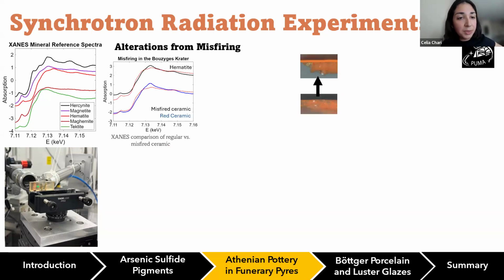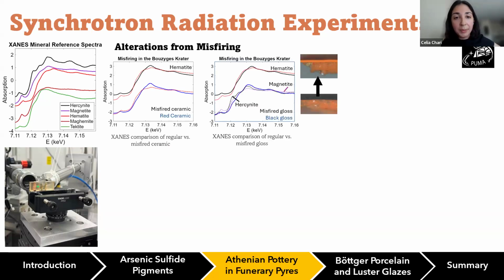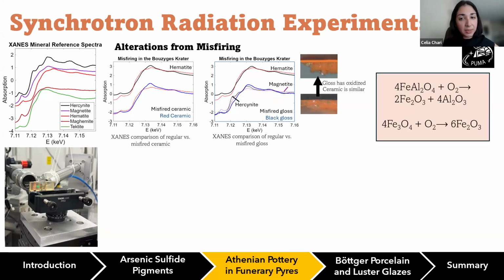We saw that when it came to the ceramic, in both cases, they're rich in hematite. And then with the black gloss, the original black gloss was rich in hercynite and also contained signs of magnetite, while the red gloss is rich in hematite. So here we have evidence for the oxidation of the gloss, while the ceramic looks similar in both cases. We proposed mechanisms for this oxidation of the black components, so the hercynite and magnetite particles within the black gloss,